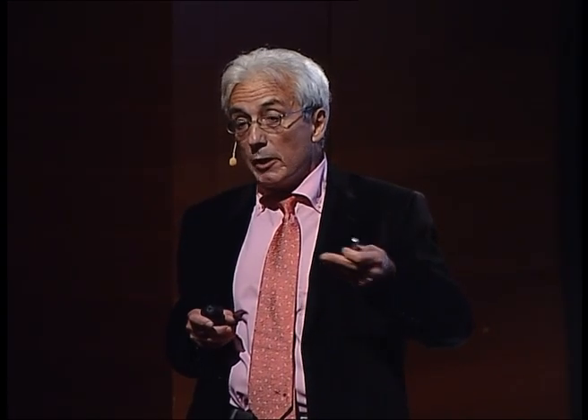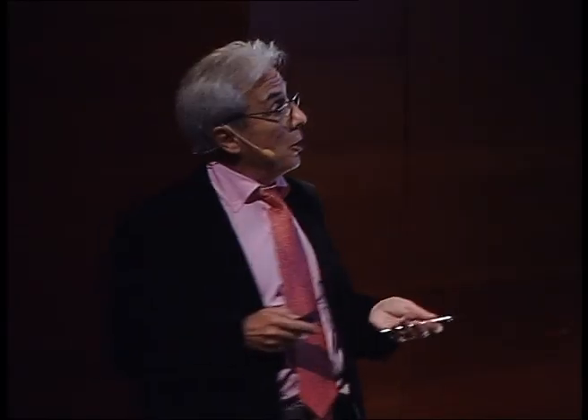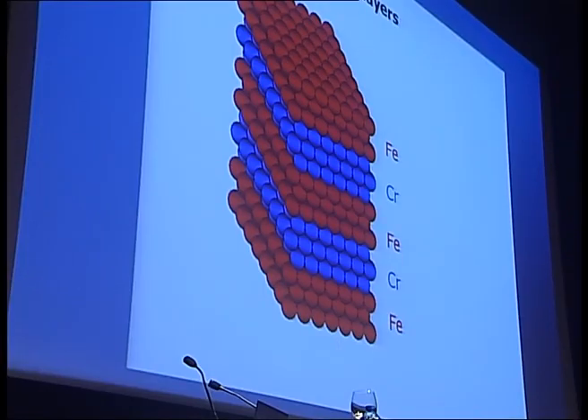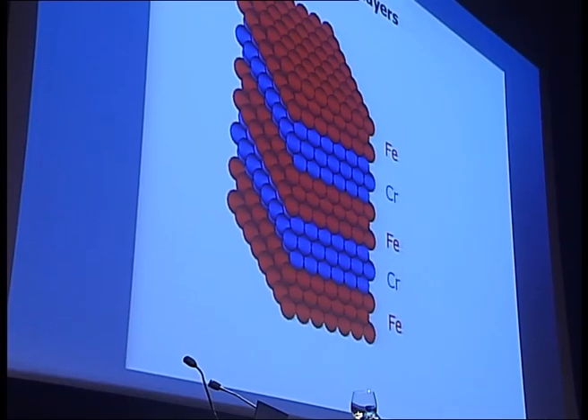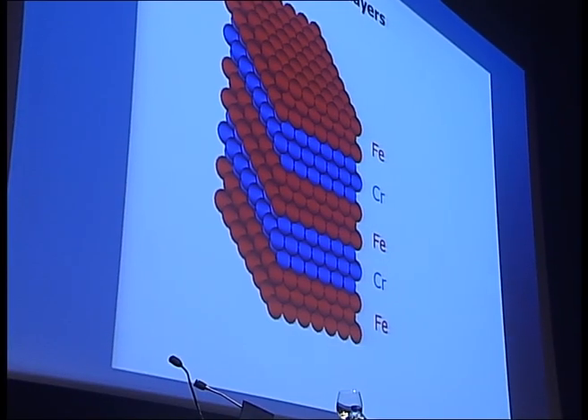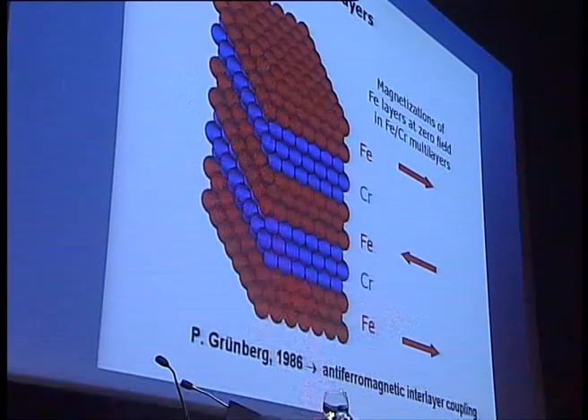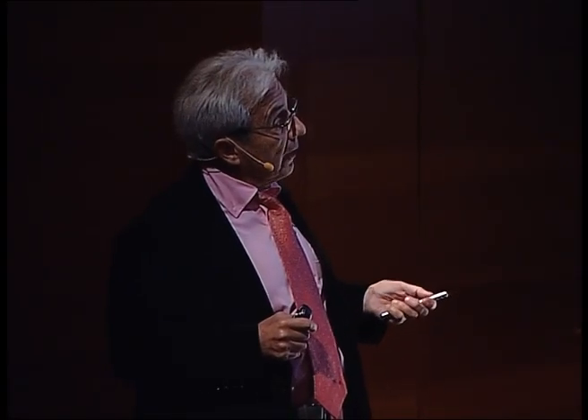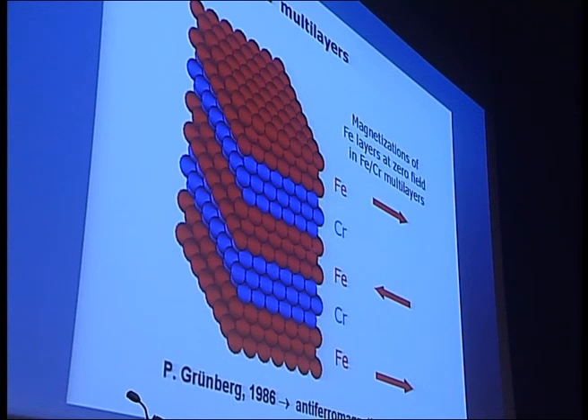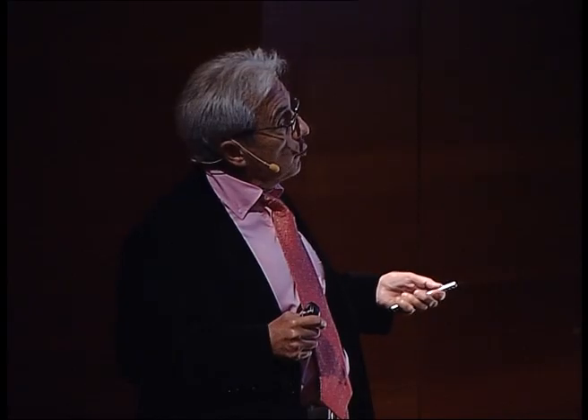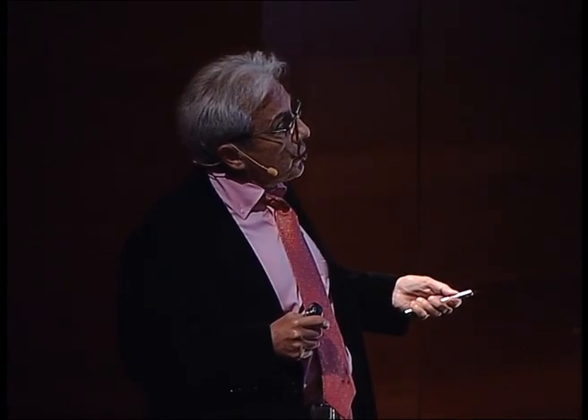But in the 80s, with microelectronics, it became possible to prepare this sort of very thin multilayer with technology like molecular beam epitaxy. And so we had a collaboration with the microelectronics company Thomson to prepare this sort of multilayers. You see the balls represent atoms, 3 atomic layers of iron, 3 atomic layers of chromium, etc. Why chromium and iron? Because Peter Grünberg, my fellow Nobel Laureate, found in '86 that for a very thin layer of chromium, there was an exchange interaction, a magnetic interaction if you want, between the two adjacent iron layers, so that the magnetizations are in opposite directions.